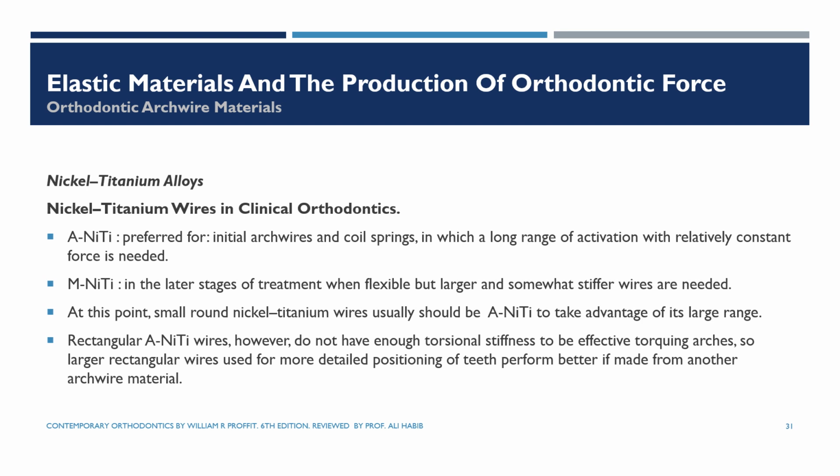Some people still use rectangular A-NiTi, but he's saying that A-NiTi doesn't have enough torsional stiffness to induce any kind of torque. So if you want to use rectangular wires, maybe you should use large rectangular wires in other materials like M-NiTi, TMA wires, or stainless steel wires.